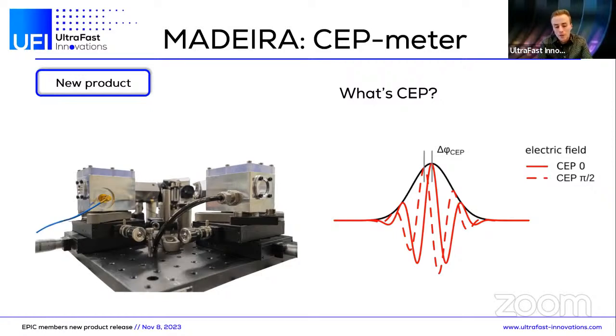And this is very important because there are laser sources that produce short laser pulses, but that do not have a stable carrier envelope phase, which means that it changes from pulse to pulse. And if you do an experiment that depends on the carrier envelope phase, it is necessary to measure this carrier envelope phase in a single shot way. But also for diagnostics of laser systems, it's important that you can verify that the carrier envelope phase of a system that is supposed to be carrier envelope phase stable is stable on a single shot basis.